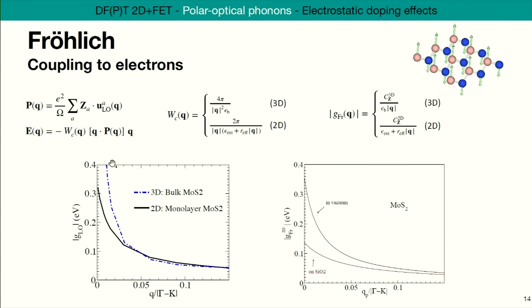In 2D, however, because this Coulomb interaction has different variation on the momentum, there's no divergence anymore. This linear term that we saw is important in the short wavelength limit goes away, and you end up with the bare coupling divided just by the dielectric function of the environment. And this is finite. It doesn't diverge anymore, and this is what we see here.